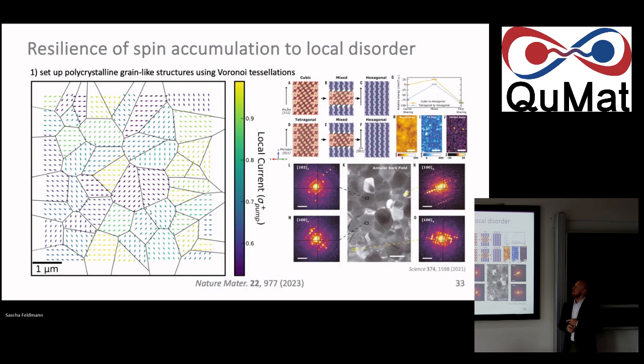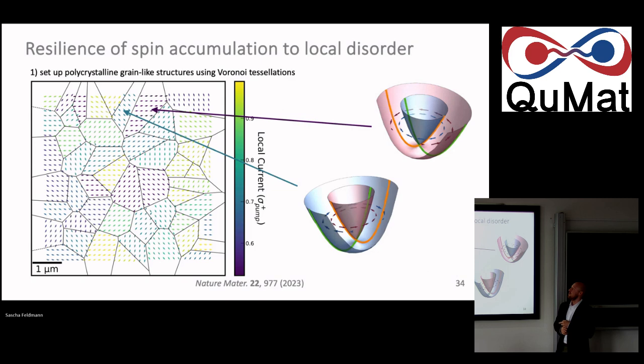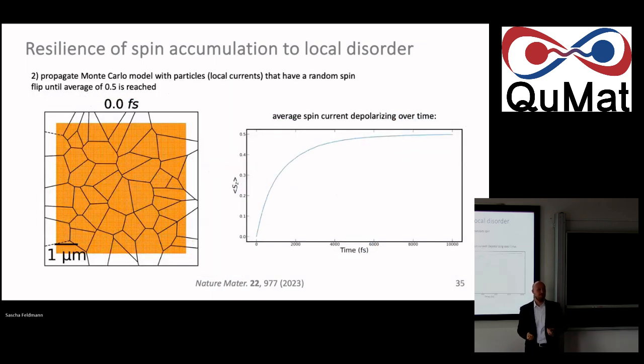We can then model this a little bit. Here we set up this polycrystalline structure, now with different domains, using Voronoi tessellation. It's a little bit overkill. And we can just say I give this one grain one spin texture and the next grain the other spin texture. And then I just flush the whole system with, say, spin up population at time 0,